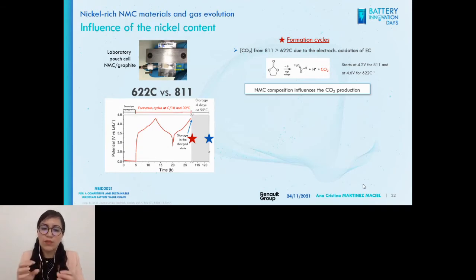But we were able, through some other experiments, to deduce that this is due to the electrochemical oxidation of EC, ethylene carbonate, through this reaction. So this is how NMC composition actually influences CO2 production.